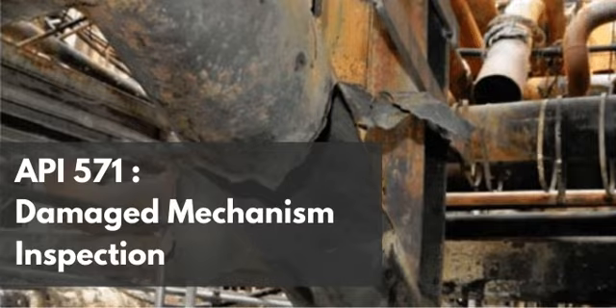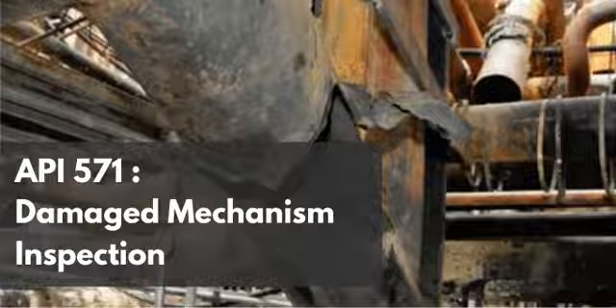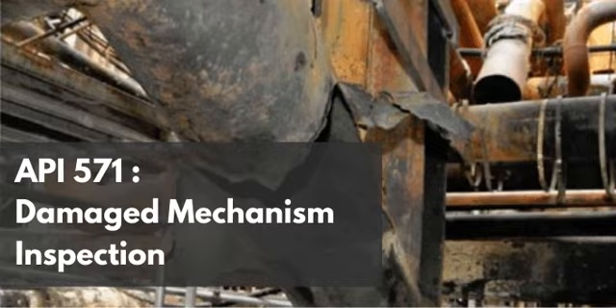It truly is. But why the weld? What is it about the weld that draws the attack? Well, it's the perfect storm of the variables we just discussed. First, the welding process creates a heat-affected zone, or HAZ, where the grain structure of the steel is altered, sometimes making it slightly more susceptible chemically. Right. But more importantly, the weld creates a physical profile. Even a good weld often has a root pass that protrudes slightly into the internal pipe.